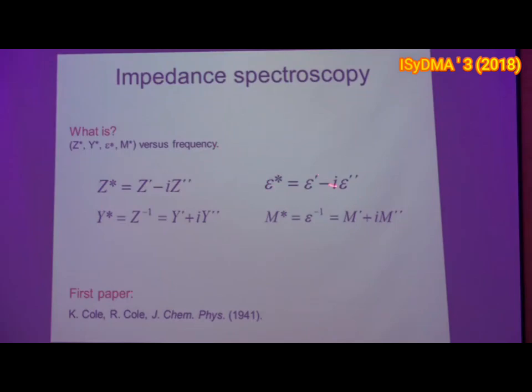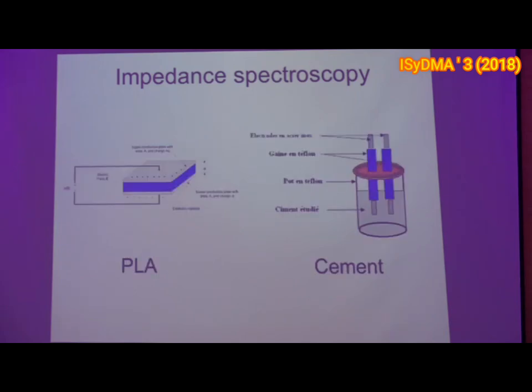Sometimes we do not have enough data or good data to make conclusions with this permittivity, and then you calculate the inverse that you call the modulus, in particular if you have materials with enough conductivity. But we can calculate these 4 different quantities: impedance, admittance, permittivity, or modulus. So I will show you two applications of aging, how we can see the aging of a material using impedance spectroscopy.